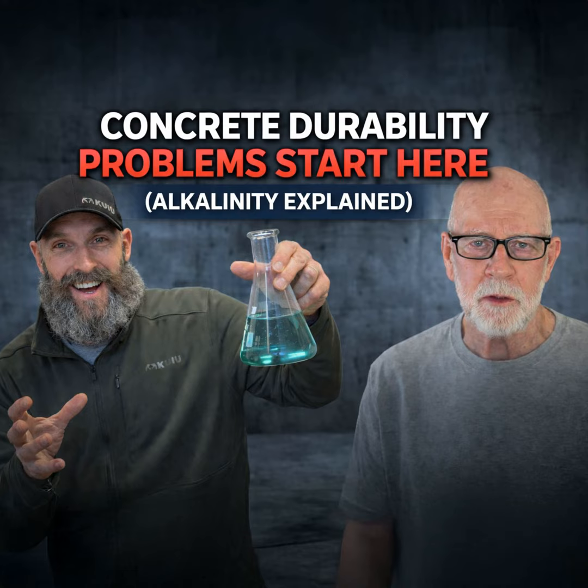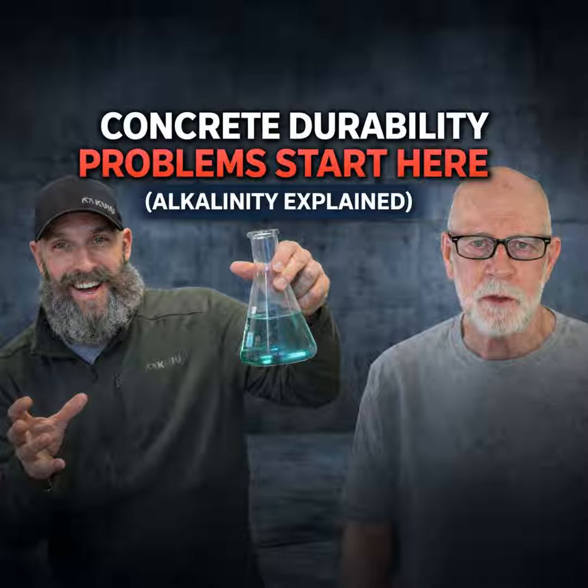And that's one of the chief causes of slab sweating syndrome. When you get older concrete, because older concrete tends to collect a lot of the salts at the surface. So when the relative humidity gets to around 75 or 80, it looks like somebody took a shower. The concrete's wet and then it dries out. So that's a sign that your concrete has a high alkalinity. Yeah, towards the surface. Correct.